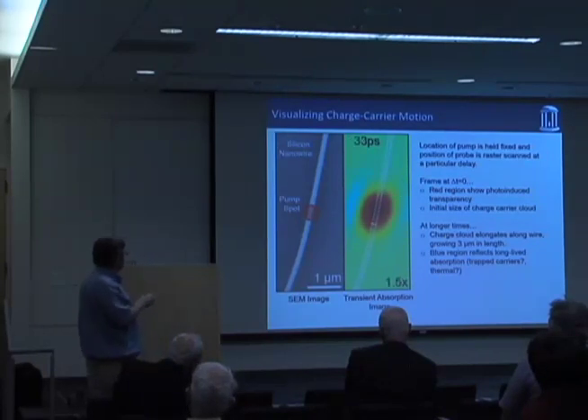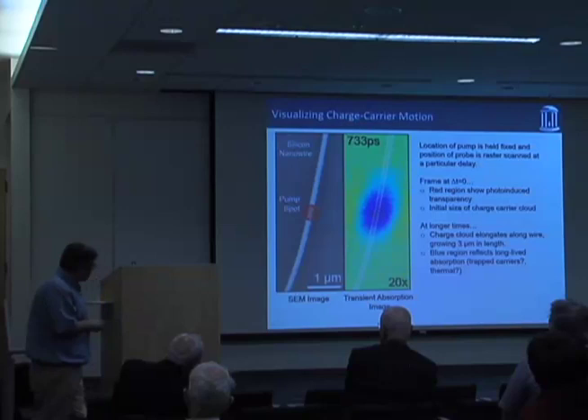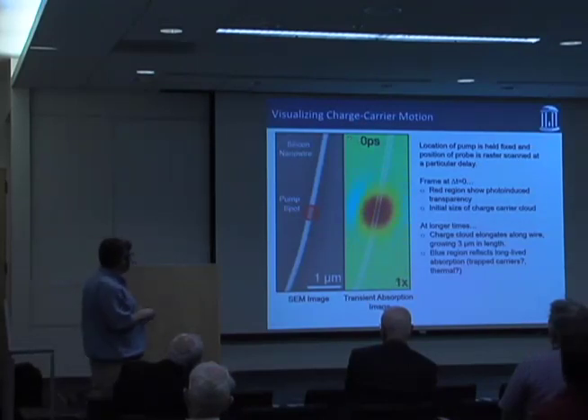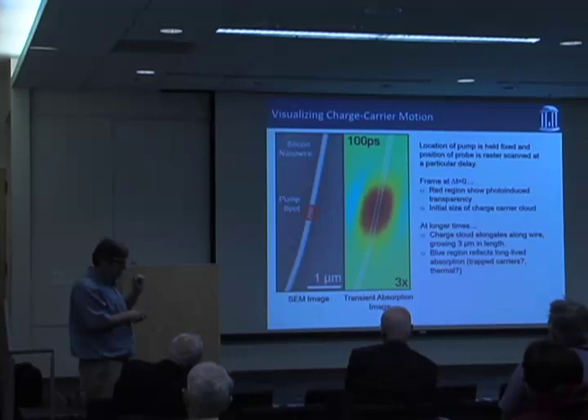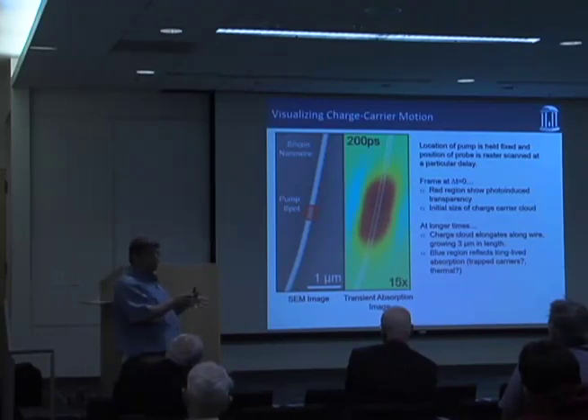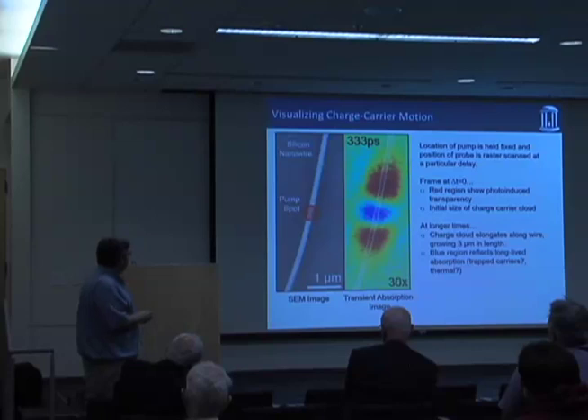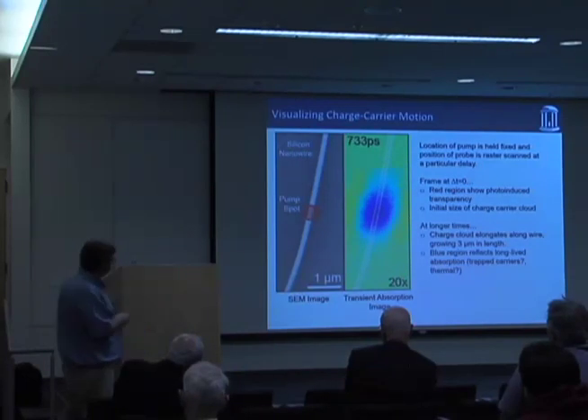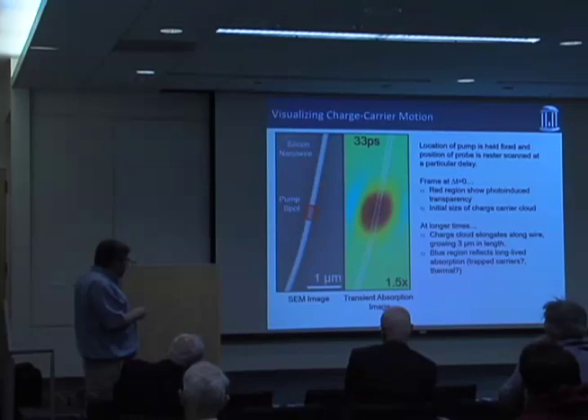The blue thing that ends up in the latter frames is photo-induced absorption, and that's always there at long times. But what's interesting is you can see that it spreads as well, which led us to think that it had to do with trapped carriers. But it could also be thermal effects that were exciting the wire and heating up a small section of it, which then spreads along the wire as well. So we can directly image this carrier motion. It turns out that these images are great and a lot of fun to make, but you can't really do anything quantitative with them.